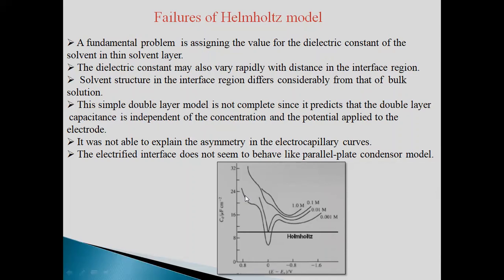As shown here, this is the experimental curve that shows that it varies with the concentration. The capacitance varies with the concentration, but as we have discussed earlier, according to the Helmholtz double layer model, the capacitance is independent of the concentration. So here we get the straight line. So it does not seem to be right. So we can say that the electrified interface does not seem to behave like a parallel plate condenser model.